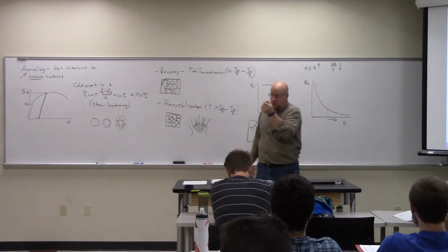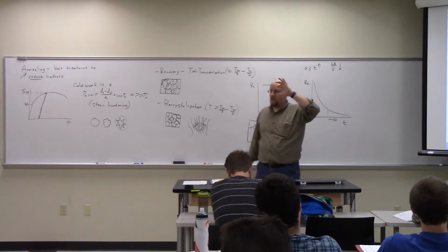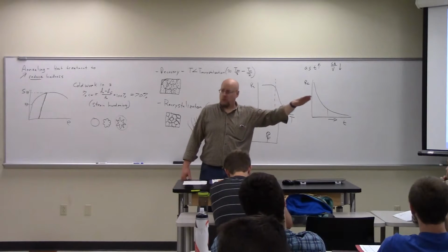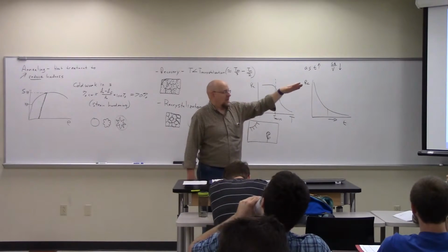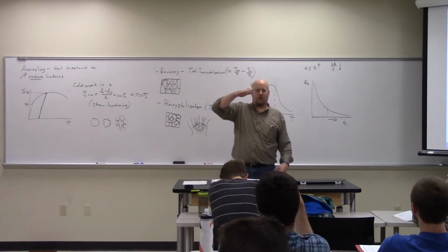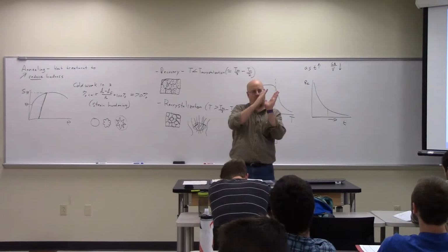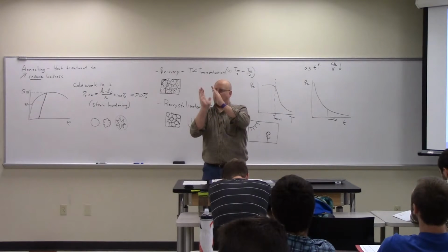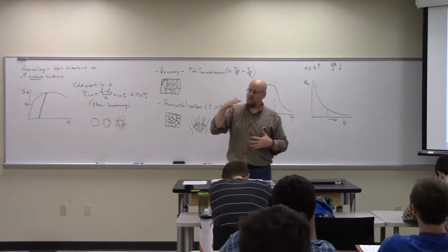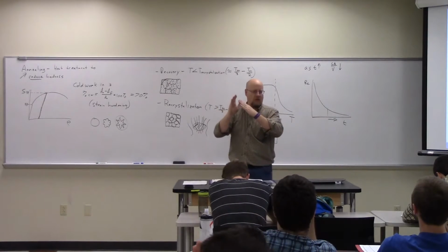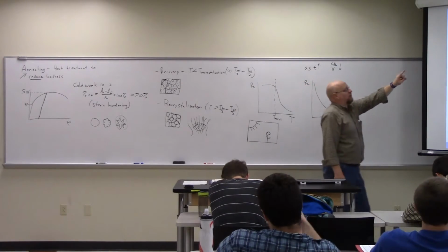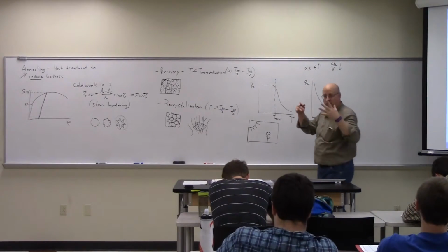So now these grains, instead of being microscopic, are macroscopic. You can see the individual facets. It looks like facets, but in reality, if I put my hand across there, it still feels smooth. Each of the grains is in a different orientation. What you're seeing is the faceted structure: in one of them, the atomic planes are like this, in the other one, the atomic planes are like this, another one, they're like this. So you get all these different atomic planes at each of the different locations, and you get different reflection off the surface. As a result, it looks like this cool granular pattern because you can see the grains.